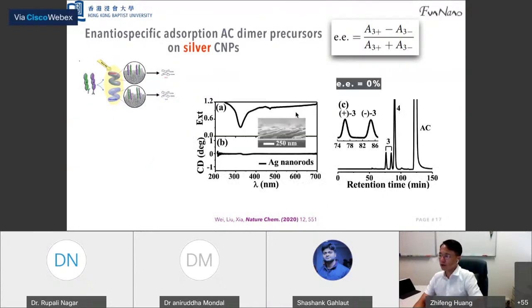And we have a control experiment, right? So rather than using the helical surface, we generate the silver achiral nanorod, so they do not have chirality on the surface. And we were very excited to find that, right? The EE value is equal to 0. Right, so that demonstrates that the chiral surface really played a very important role for this asymmetric synthesis.